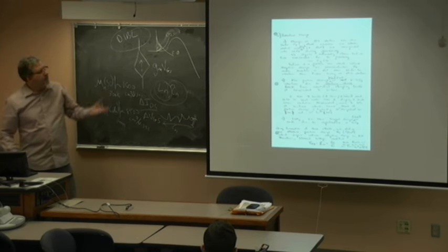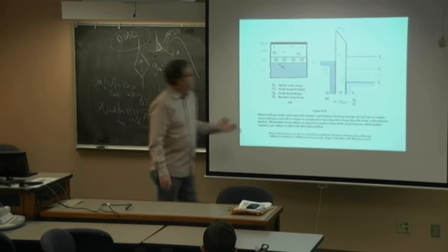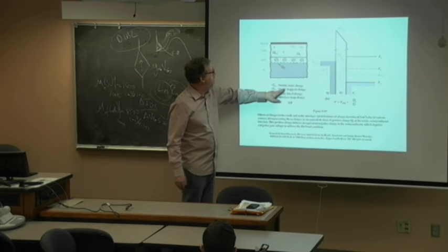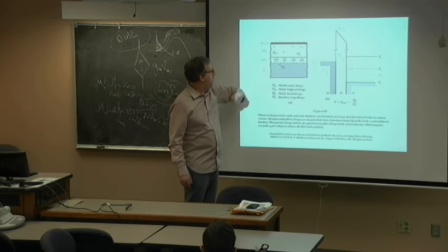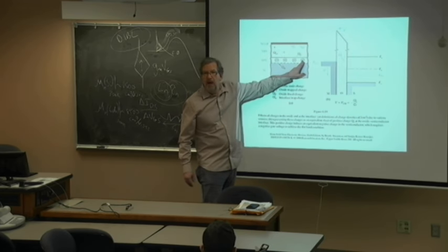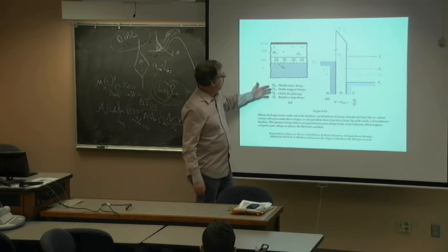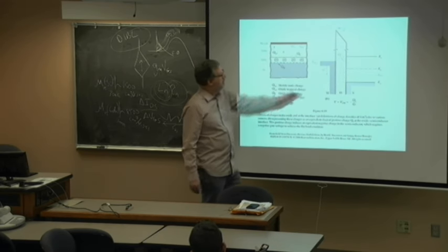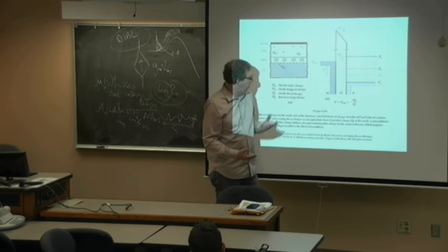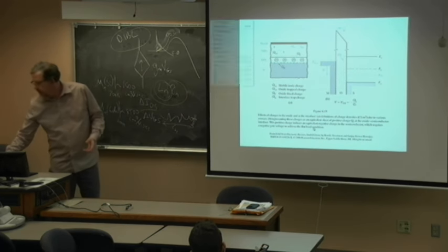So then we have all that interface state charge, which is maybe better shown here, where I can have charges that are mobile ions moving around, like sodium and potassium. I can have oxide trap charge, where I have defects in my oxide. I can have oxide fixed charge. I can have interface trap charge due to maybe dangling bonds or contaminants. And so all these different sources lead to an overall Q_I of undesired charge near this interface. And that Q_I, the aggregate undesired charge, you can never avoid it, adds another term to the equation.